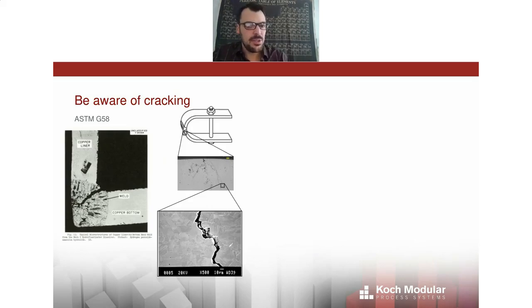Process engineers doing scale up should also be aware of cracking. It's not enough to just test for wall loss. If the corrodant forms cracks in your metal, that won't necessarily show up in a weight loss test. It tends to be the case that either welds or the heat affected zone around the weld are the most susceptible to cracking. So you can pick this up in a more rapid test by using a welded and stressed coupon. The diagram at the top shows the fillet weld, and then the welded section is then bent into a horseshoe shape to put it under stress. There's a lot of tensile stress on the outside radius, which once subjected to a corrodant should rapidly show cracking phenomenon if it's going to occur.